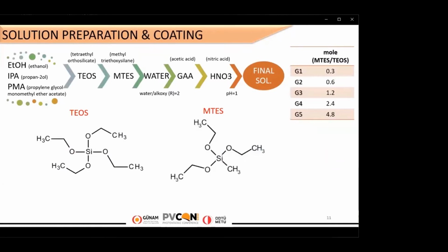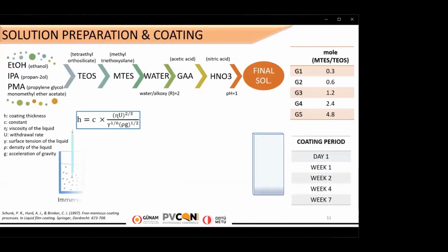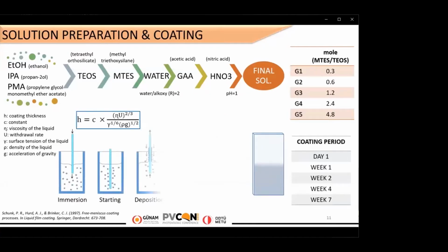We used as a solvent ethanol, propanol, and PMA mixture, and as a precursor, we used dual alkoxysilanes, which are tetraethyl orthosilicate and methyltriethoxysilane that you can see in figures. Finally, we added acetic acid as an organic acid and nitric acid as an inorganic acid together as catalysts. We determined the exact ratios of all ingredients by experimenting, except silanes. We have determined the silane groups as variables, and you can see 5 different ratios coded as G in table. We use dip coating method, as I said before, and here are the steps of this method.